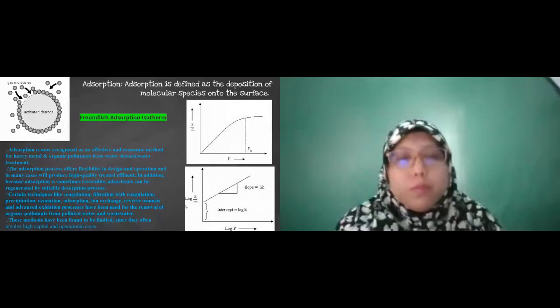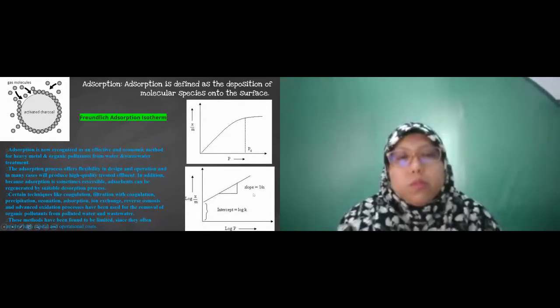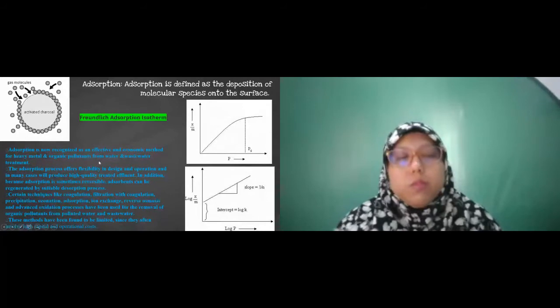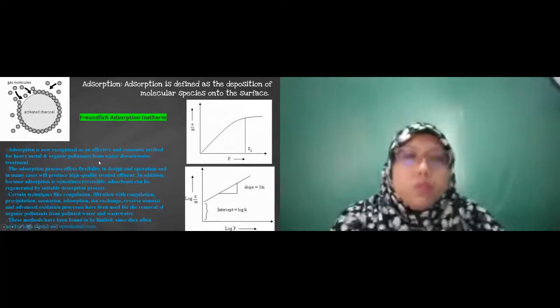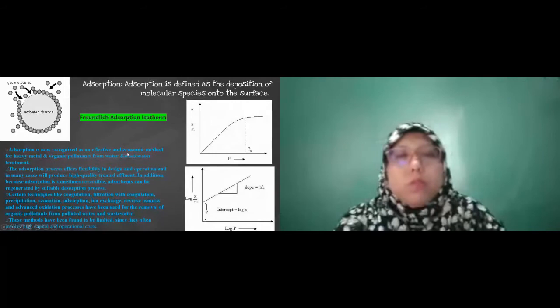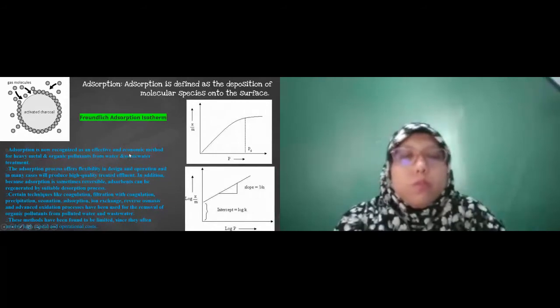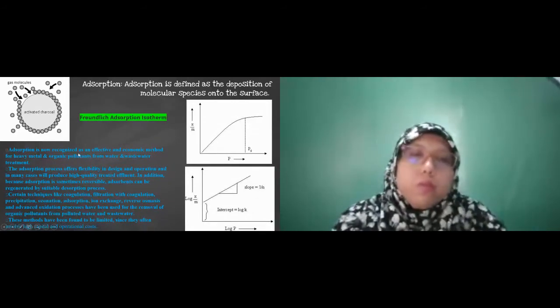So adsorption by activated carbon, as you can see here, is just the molecules adsorbed on the surface. When we convert it to the isotherm, if we get the slope 1/n less than 1, then we understand that the adsorption is good. This adsorption is effective, as I said, because it is a very economic method, and very effective as well for heavy metals and organic compounds.